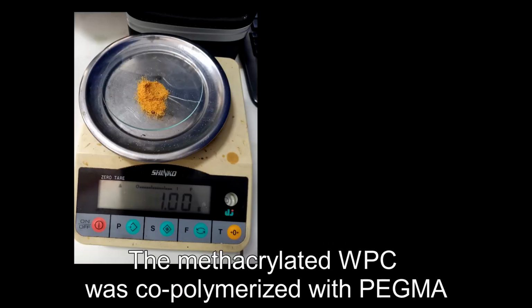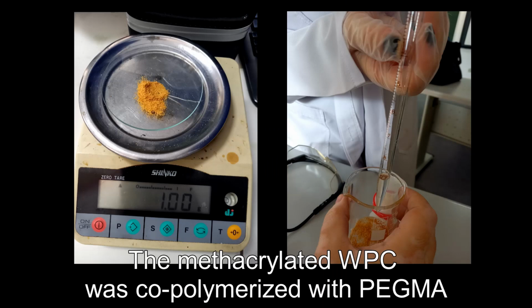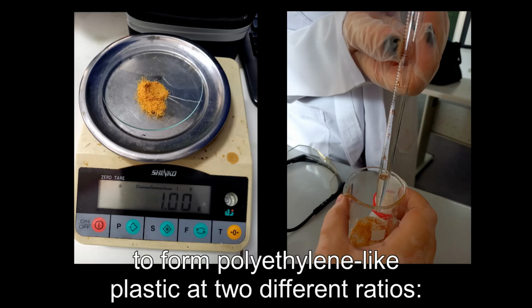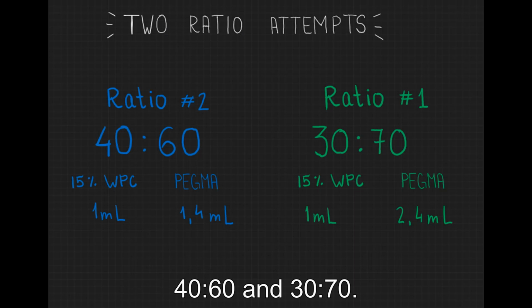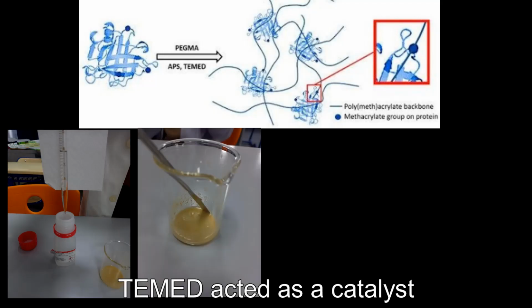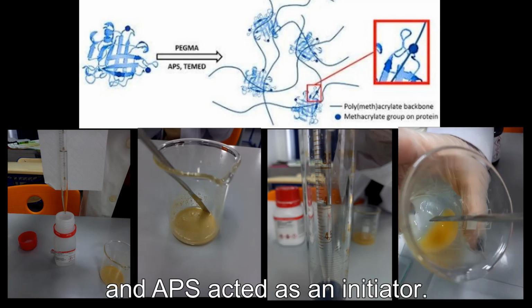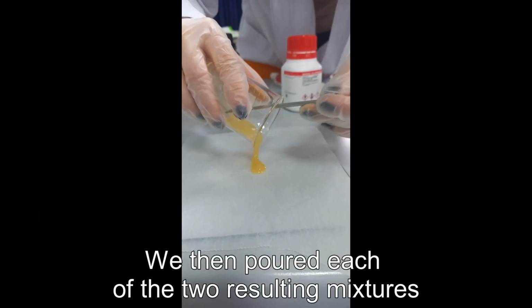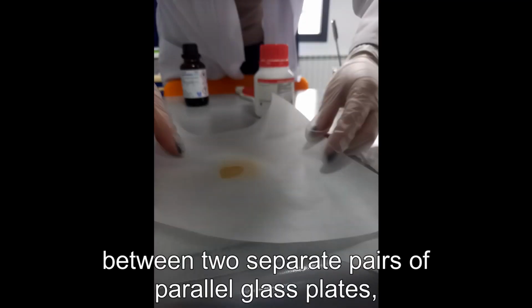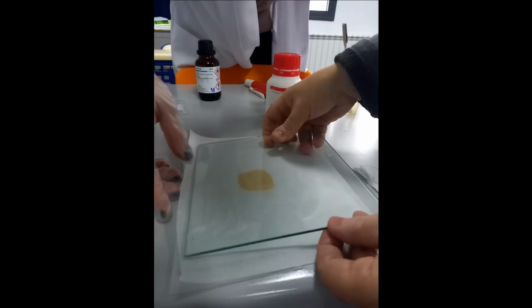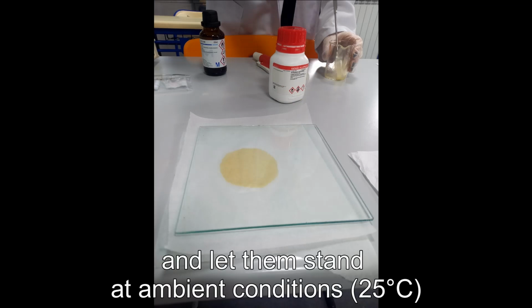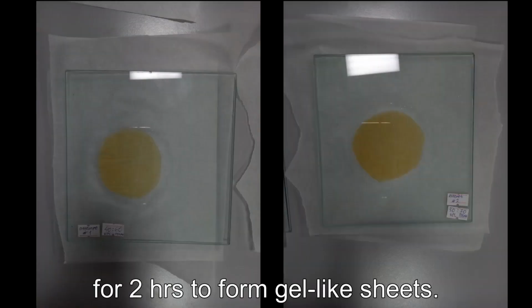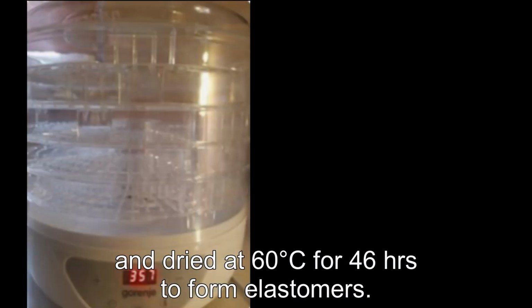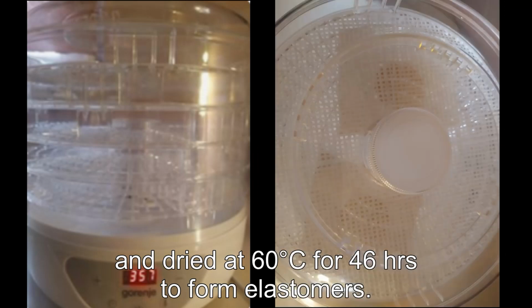The methacrylated whey protein concentrate was copolymerized with PEGMA to form polyethylene-like plastic at 2 different ratios, 40:60 and 30:70. TEMED acted as a catalyst and ammonium persulfate acted as an initiator. We then poured each of the 2 resulting mixtures between 2 separate pairs of parallel glass plates and let them stand at ambient conditions for 2 hours to form gel-like sheets. The sheets were then peeled off and dried at 60 degrees Celsius for 46 hours to form elastomers.